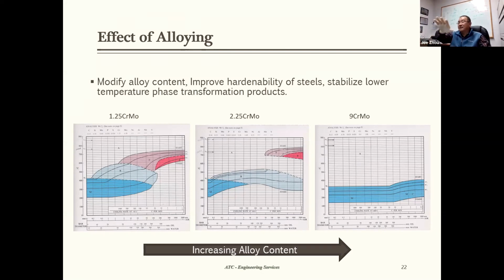Okay, you can see this CCT diagram is completely different. For 1 1/4 Cr, you have a lot of ferrite forming, bainite forming, and martensite. When you increase alloy content from 1 1/4 to 2 1/4, you are moving the upper transformation ferrite to the right-hand side. You are enlarging the bainite area. That's the reason when you compare T11 to T22, you see more bainite colonies in the microstructure. When you go into the 9 chrome, you see the entire area was martensite. So when you heat treat it at a normal cooling rate, you will see a martensite structure.